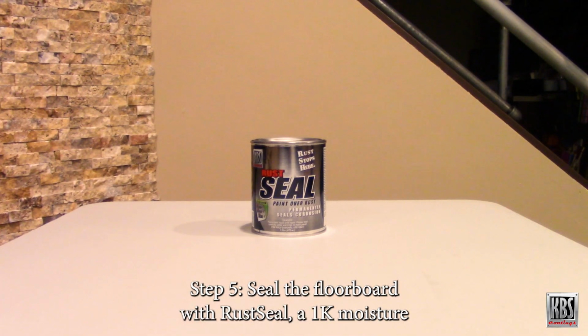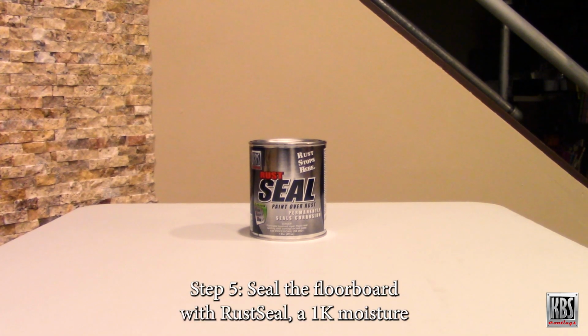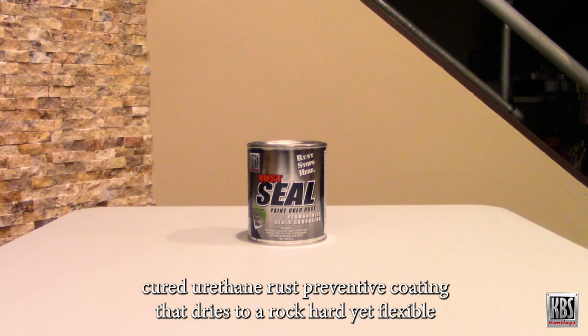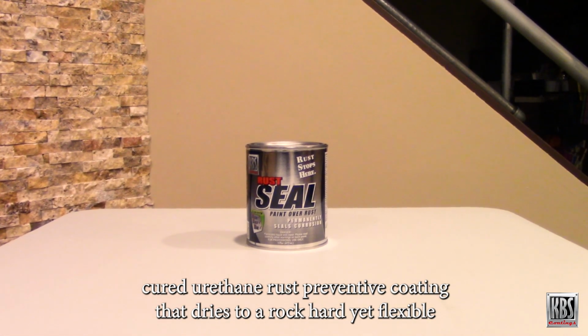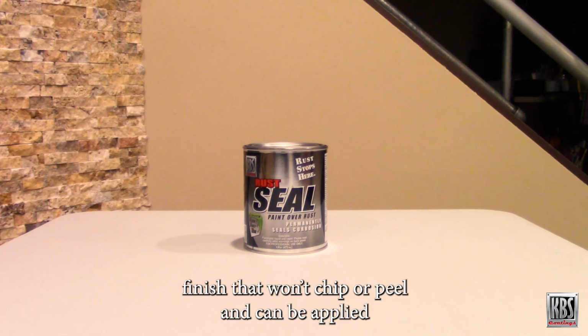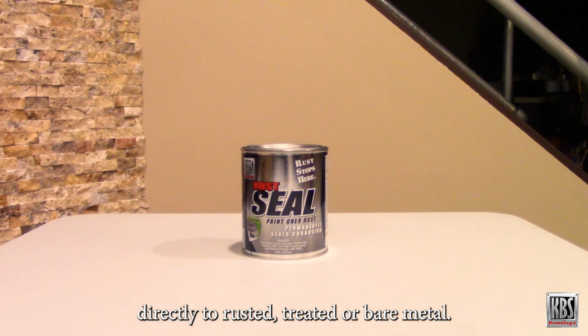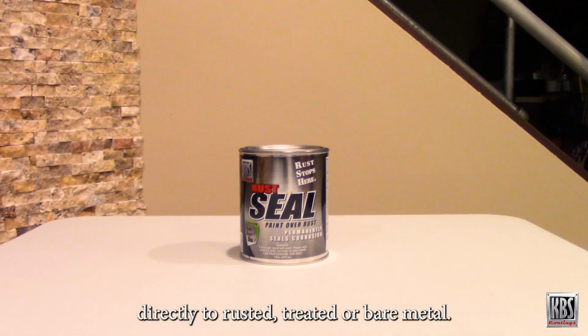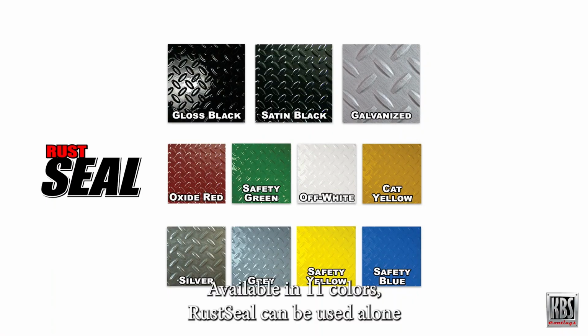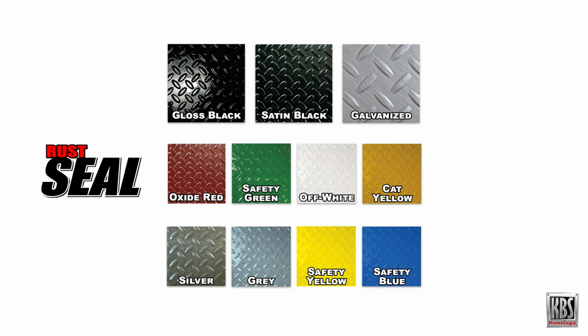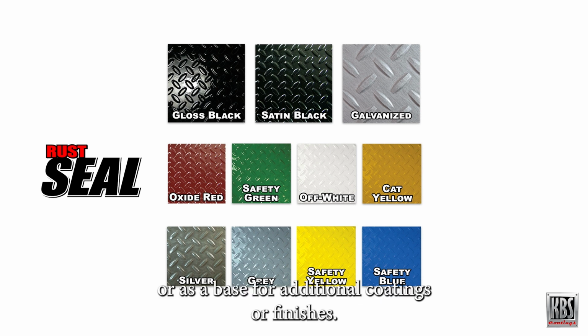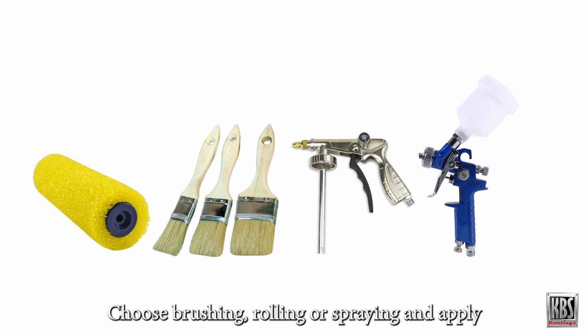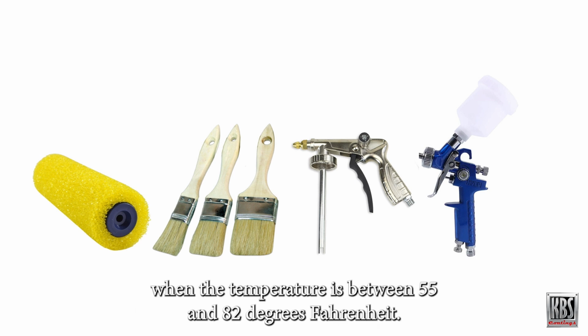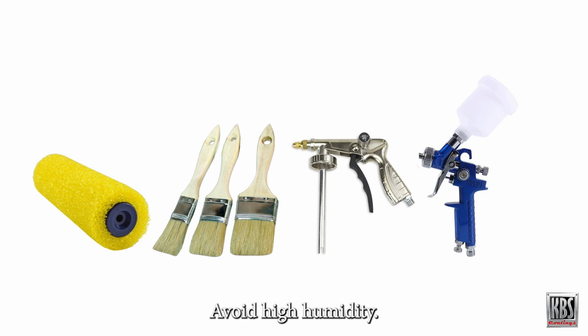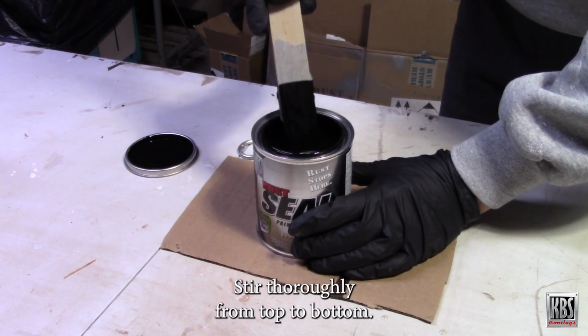Step 5. Seal the floorboard with Rust Seal, a 1K moisture-cured urethane rust-preventive coating that dries to a rock-hard yet flexible finish that won't chip or peel and can be applied directly to rusted, treated, or bare metal. Available in 11 colors, Rust Seal can be used alone or as a base for additional coatings or finishes. Choose brushing, rolling, or spraying and apply when the temperature is between 55 and 82 degrees Fahrenheit. Avoid high humidity. Stir thoroughly from top to bottom.